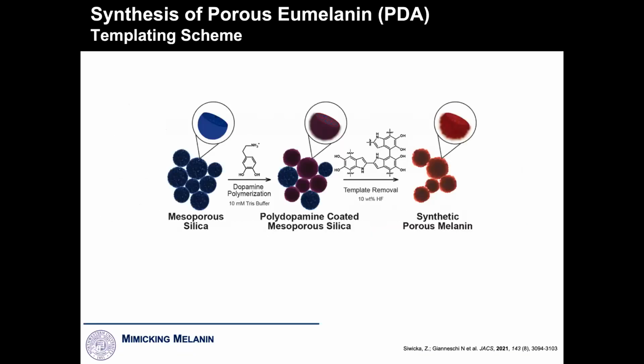One of my grad students, Zofia Sawicka, who's the first author on this paper, talked me into this. I originally said it probably wouldn't work, but she worked really hard and got it to work. What she did was take mesoporous silica, which is silica with nanoscale pores, and template on it. She grew melanin on the surface, but also inside the silica. And then she etched it with HF, which is the bone melter. It's a pretty dangerous chemical, which is part of the reason I didn't want to do it. But it works really well. We end up with a porous melanin material that's templated, so it has the same or very close porosity to the original porous silica. And I'll come back to these particles in a sec.